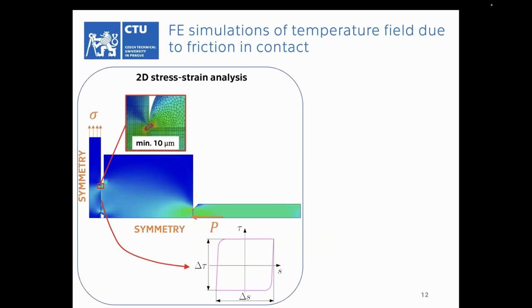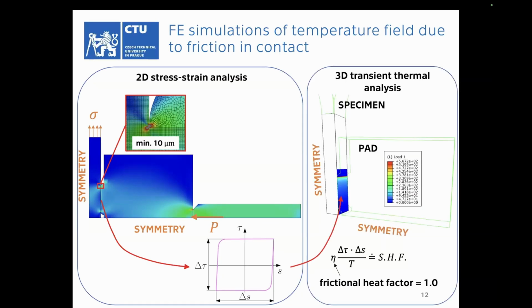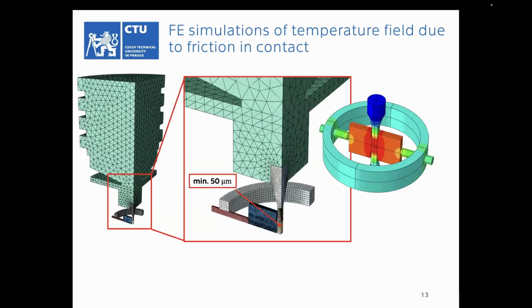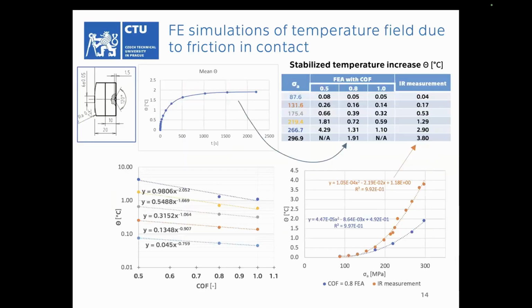So to do so, we have created the models for uncoupled thermomechanical analysis, a 2D model to compute contact slips and shear stress. From their ranges, we have computed surface heat flux, which was then mapped to the contact surface as a boundary condition in the transient thermal analysis. This is a detailed view of the model for thermal analysis, sample output, and here are the stabilized temperatures from this analysis. We have created a set of computations with different stress amplitudes on different levels of coefficient of friction, because at the time of doing this analysis, we didn't have data from digital image correlation.